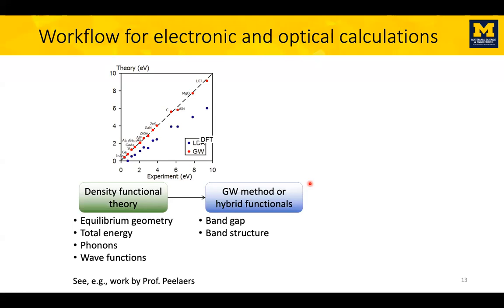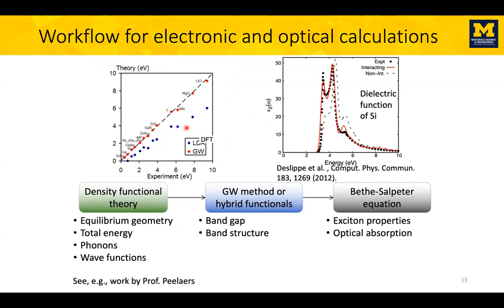So the first thing we do is calculate the band gap. And for the band gap, that's where DFT does not do very well. DFT typically underestimates the band gaps of insulators by about 50%. And so we come with methods either based on hybrid functionals that mix in part of exact exchange, or methods based on diagrammatic perturbation theory, such as the GW method, which give us very accurate band gaps as well as band structures. And once we have band gaps and band structures, we can do things like study optics, study excitons, study transport, and all the responses of the material we're interested in.